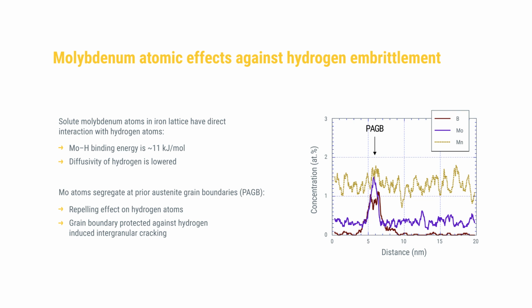The tendency of a steel to be subjected to hydrogen embrittlement can be lowered by optimizing the steel in terms of microstructure, but also in terms of what we call hydrogen traps to bind the hydrogen at certain features that are not so critical. And molybdenum alloying can play a significant role in achieving these microstructures and also in providing these traps.